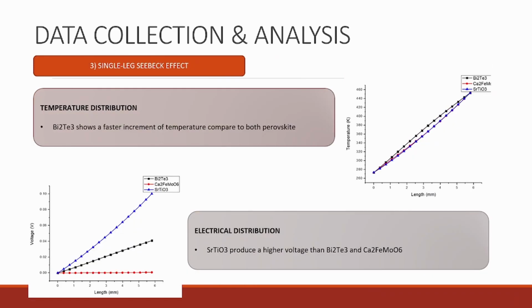The data collection for the single leg Seebeck effect: for the temperature distribution, bismuth telluride shows a faster increment of temperature compared to both perovskites. And for the electrical distribution, strontium titanate produces a higher voltage than bismuth telluride and calcium iron molybdate.